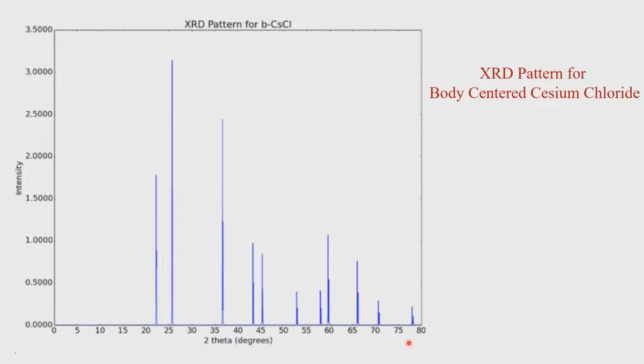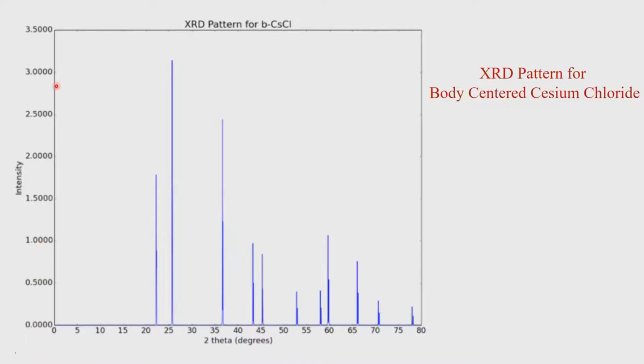So, that way we know when we do an xy plot of this kind that all information on the geometry is here, and all information about the structure is along the y direction, because the intensity is the one which is telling us which atom is where, and therefore the electron density distribution is covered along the y axis. So, the information that is present along the y axis tells us about the way in which atoms are distributed inside the unit cell.